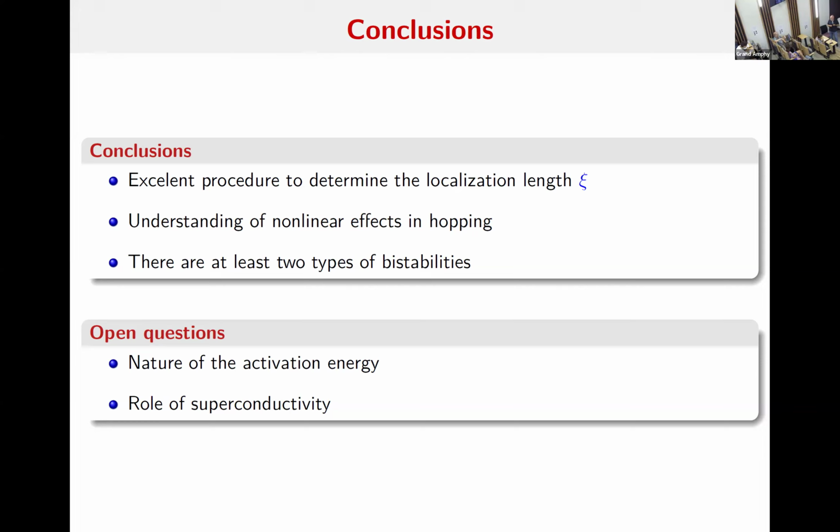Because the 6th power law you get only in the normal state. If you have a superconductor, there is a delta that also has an activating gap like component coupling. The second point is that usually you get the 5th power in a 3D metal. The 6th power you can get for disordered metals, at least in theory by Kaplan. That depends a bit on how the disorder moves. That would require that your grains are also disordered.